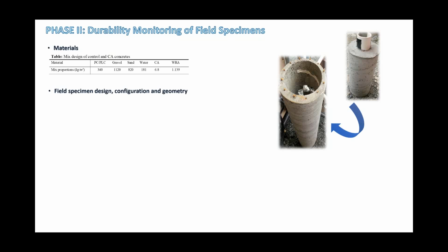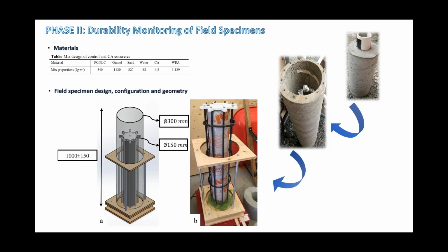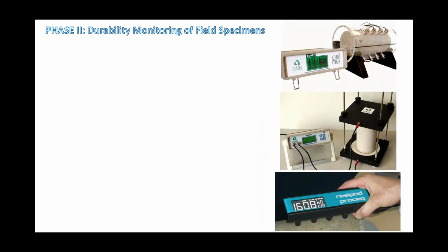Then when I cast bigger samples, our goal was to have the column with 4 feet height. Then I realized that all of the rebars should be somehow concentric. So I went further and designed a model in SolidWorks. And as you can see, I managed to get a mold which can satisfy all these requirements. Using this mold, which has been manufactured here, I was able to cast